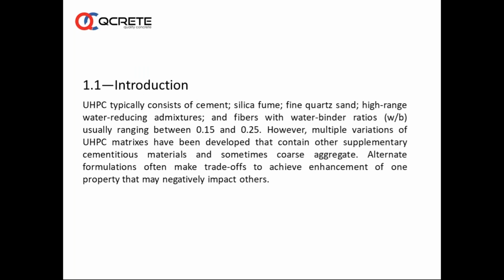Ultra high performance concrete consists of cement, silica fume, fine quartz sand, high range water reducing admixtures, and fibers with water binder ratios probably between 0.15 to 0.25. And many times, a lot of variations in UHPC matrices have been developed that contain other supplementary cementitious materials and sometimes coarse aggregate.